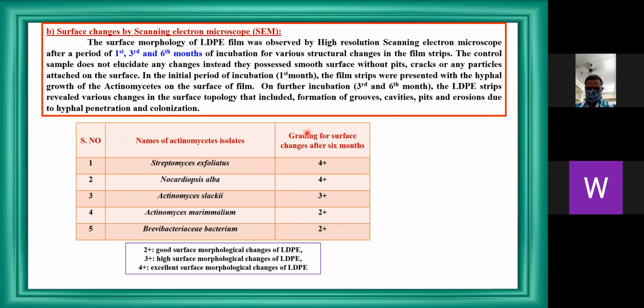Surface changes by scanning electron microscopy. The surface morphology of the LDPE film was observed by high resolution scanning electron microscopy after a period of 1, 3, and 6 months of incubation for various structural changes. The control sample does not show any change. Instead, it possesses a smooth surface without pits, cracks, etc.